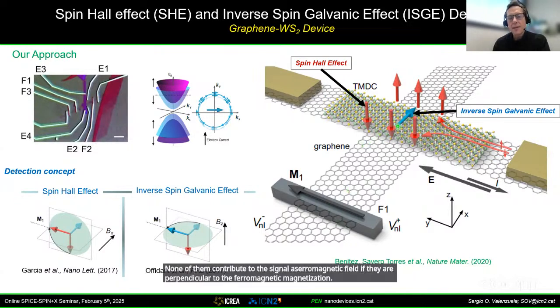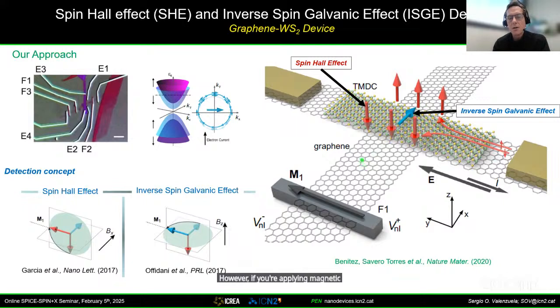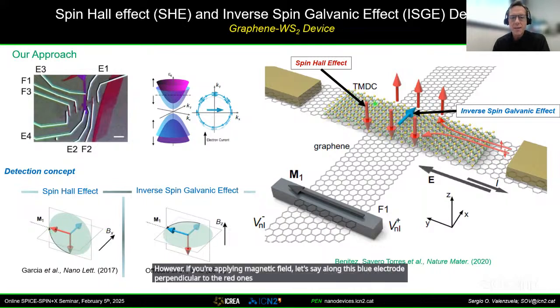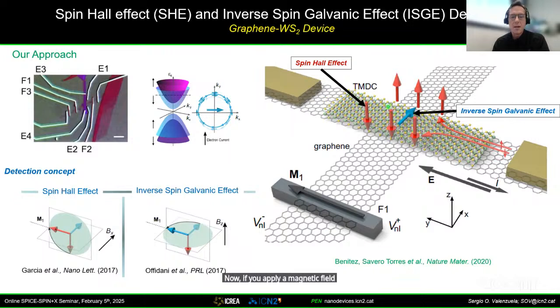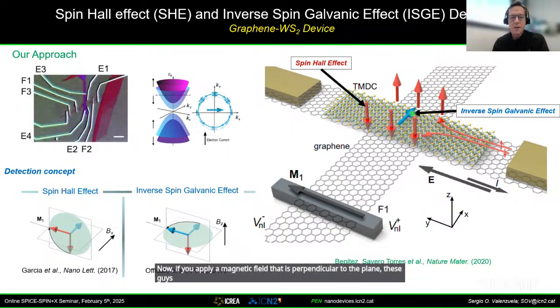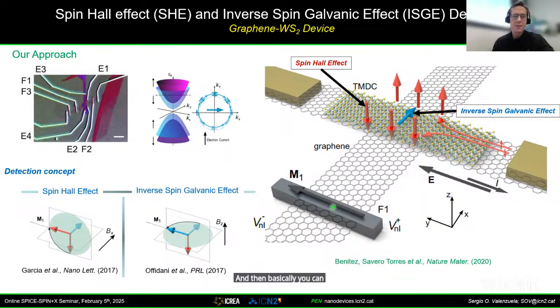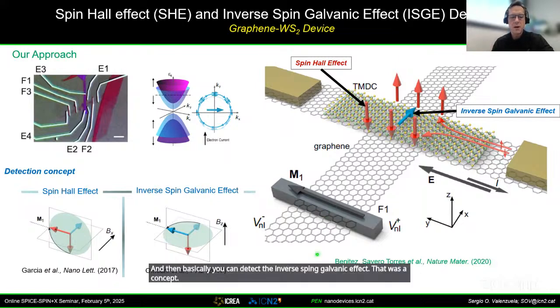However, if you apply a magnetic field, let's say along this blue electrode perpendicular to the red ones, in this case, you make the spins that are due to spin Hall effect precess, and then you detect the signal. Now, if you apply a magnetic field that is perpendicular to the plane, these do not precess, but this one precesses, and then basically you can detect the inverse spin galvanic effect. That was the concept. This is described here.